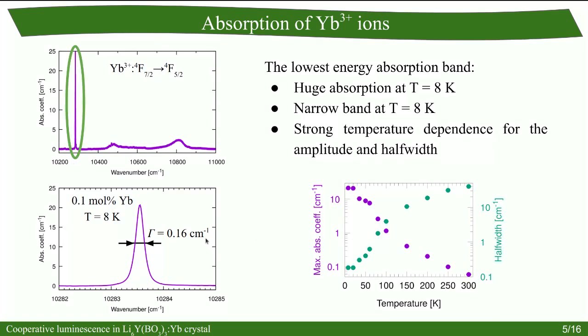At low temperature, the very narrow band means that the half-width of the absorption band is only 0.16 reciprocal centimeter, which can be measured only with a very thin sample doped with only a small quantity of ytterbium ions. Here you can see that the absorption coefficient is 20, which is very high. Here you can see the temperature dependence of the maximum of the absorption coefficient and the half-width of this absorption band. Both change by 2 orders of magnitude from 8 Kelvin to 300 Kelvin.